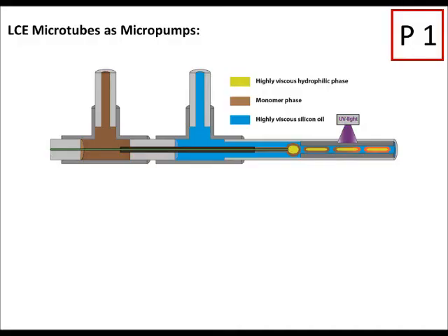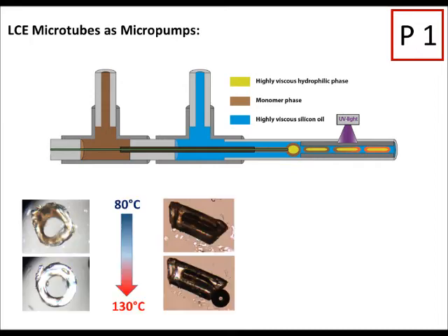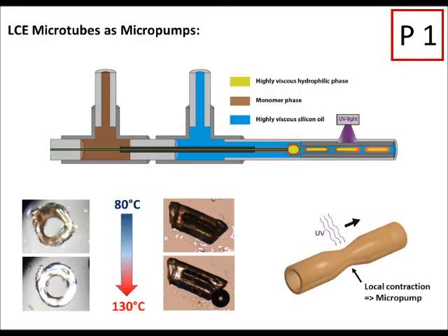Recently, we focused on the synthesis of more complex particle morphologies. With the aid of a modified microfluidic device, we managed to prepare LCE microtubes by polymerizing elongated core-shell particles. These microtubes show a thickening of the tube's wall upon heating, which leads to release of an air bubble that is trapped inside. Currently, we make these tubes photoresponsive in order to get light-driven micropumps.